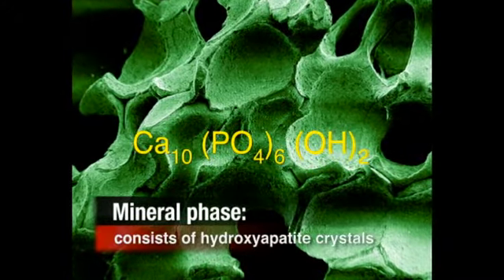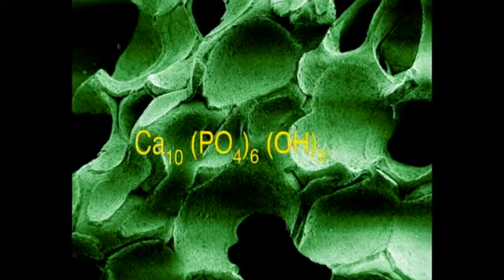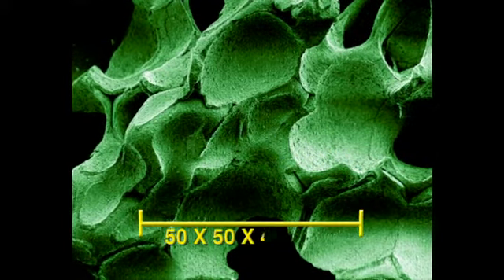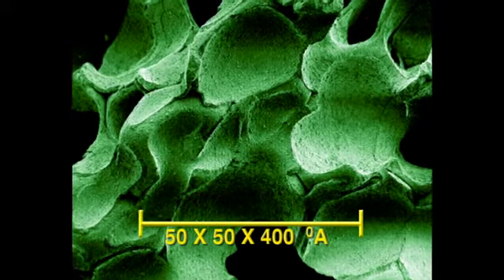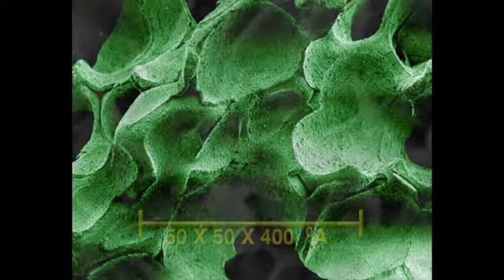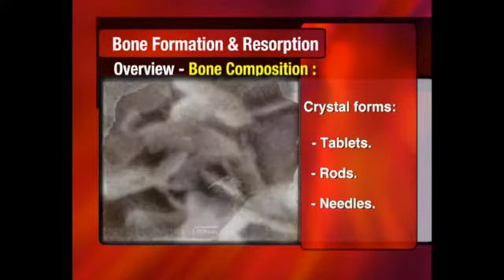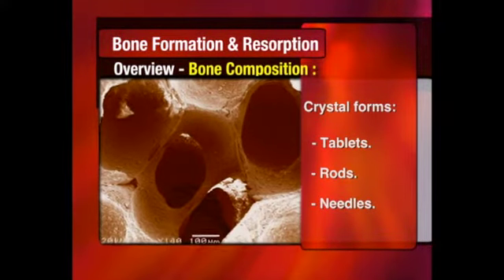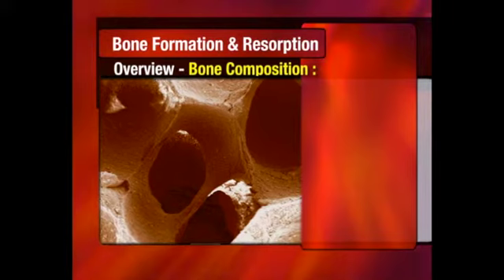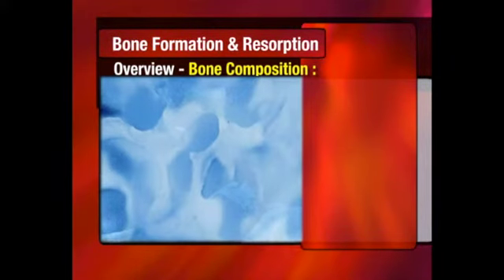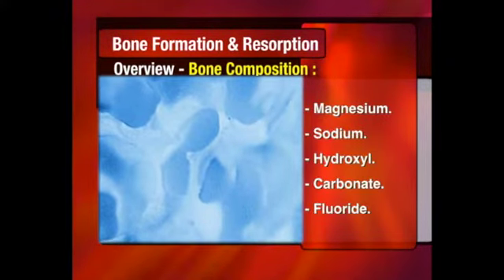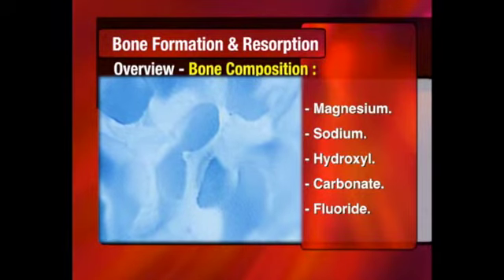The mineral phase of bone consists almost entirely of hydroxyapatite crystals. These small crystals measure about 50 by 50 by 400 angstroms. The crystals, however, can be of different forms, being described as tablets, rods, or needles. The bone material is not pure, but contains other ions by way of substitution, such as magnesium, sodium, hydroxyl, carbonate, and fluoride.